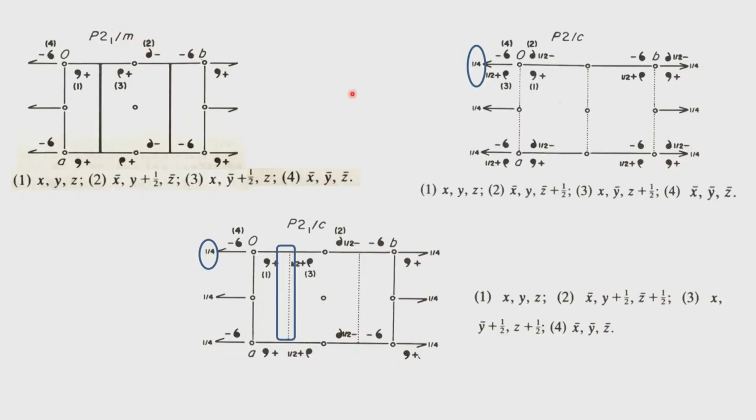And so the triclinic system has only two space groups, whereas there are several space groups which develop in the case of the monoclinic system. Further, we have also seen that the presence of the translation involved components will involve translations of the individual components, depending upon the nature of the participation of the non-translational components in the space group.